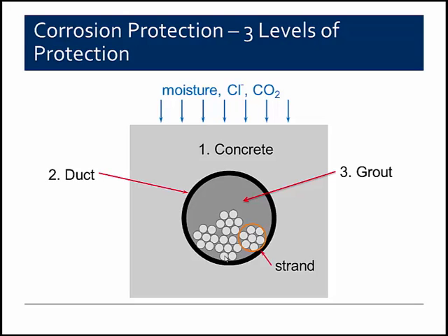And then finally the third layer of the protection system is the grout itself. Now in this diagram we've intentionally biased the locations of the strands, as they would be in a real structure, towards one side or the other of the duct. As the duct profile or direction changes, those strands orient themselves to one side or other of the duct. And so you can see that while the grout does surround them, there are locations where the grout may not completely surround the strands to provide that protection.